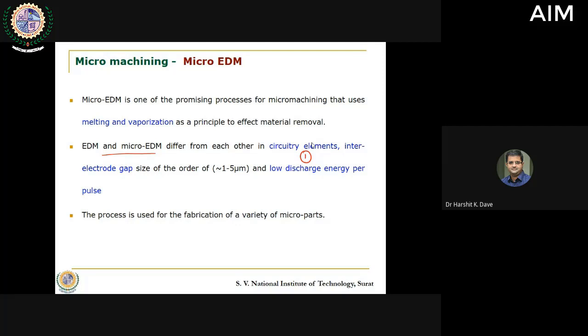The other aspect is inter-electrode gap, the gap between tool and the workpiece. So if this is the workpiece that you have and this is the tool that you are using, the minimum gap that you need to place between the tool and workpiece, or in that case when the cavity has already been generated, this distance as well as that distance is quite smaller as compared to what you have in case of EDM. Usually in EDM it is in the range of 100 microns, say 50 microns, whereas in micro EDM it is somewhere around 2 microns.